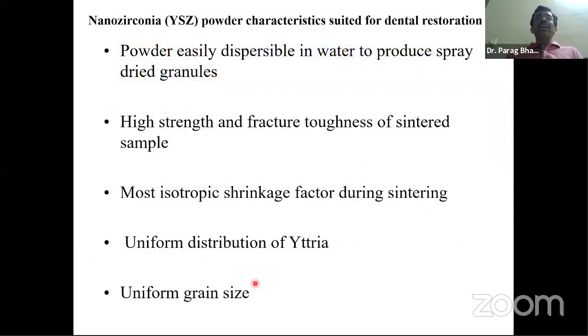So these are the characteristics of the powder. The powder must be easily dispersible in water, this nano powder, so that I can spray dry it into granules. Only when I get granules, these controlled aggregates, can they be used for isostatic pressing. I press them into discs, and then you saw those disc pictures, then I'm using it in other applications, right?